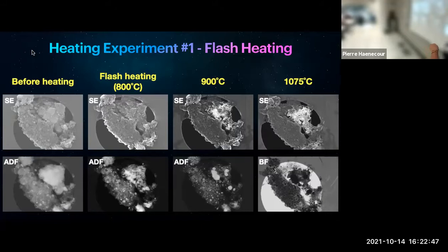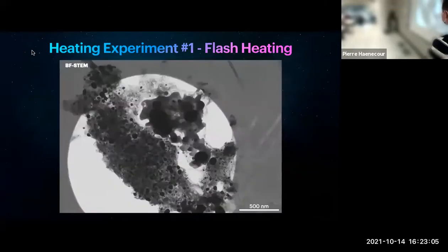So here we'll show you the bright field images. So it's basically the opposite of the dark field. What appears really bright in the dark field is black now in the bright field, but just showing you for comparison that those large nanoparticles are basically getting larger. So here you can see how it actually looks after the flash heating.